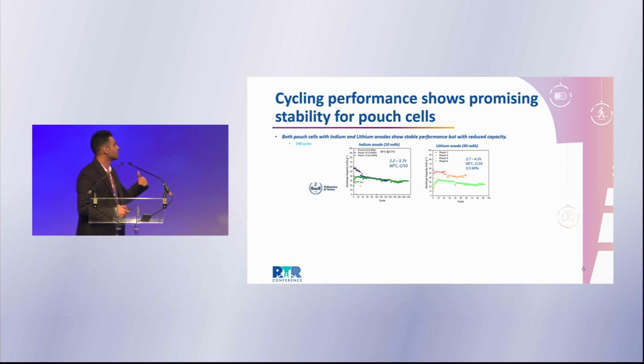However, we can see that the capacity is much reduced, and this is because the process of the electrode needs further optimization, I can say. So at the moment we have a stable cycling, so we can reach 250 cycles. The cell is working. However, in the first step, for the formation, we still lose capacity. And this is mainly from the cathodes that we have produced and the lithium metal anode, which are still decomposing a little bit in the first steps of charge and discharge.